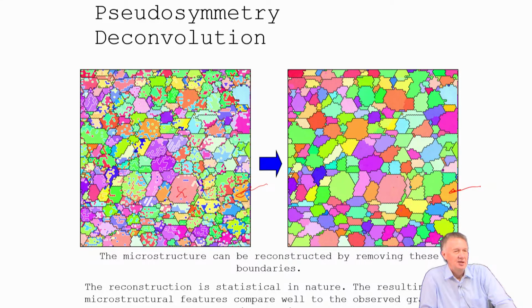So you could use relative bandwidths, and maybe if there is something in your superlattice that says this band's going to be wider if it's a superlattice and narrower if it's not, then you could define that in the phases that you use and use that as part of your indexing. I haven't tried that one actually, but if you have a band that would define well like that, then maybe that'd be a reasonable approach. Typically when I've tried to use bandwidths, it hasn't worked very well.